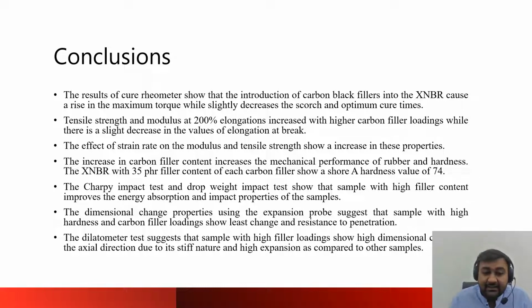The dimensional change properties using the expansion probe suggest the samples with high hardness and carbon filler loadings show the least change and resistance to penetration. The dilatometer test suggests that samples with higher filler loadings show high dimensional change due to the stiff nature of the samples. So the hardness of the sample has a major role in the mechanical performance of the rubber. The samples with high hardness show good dimensional change during a dilatometer test and show good energy absorption as compared to samples with low hardness.